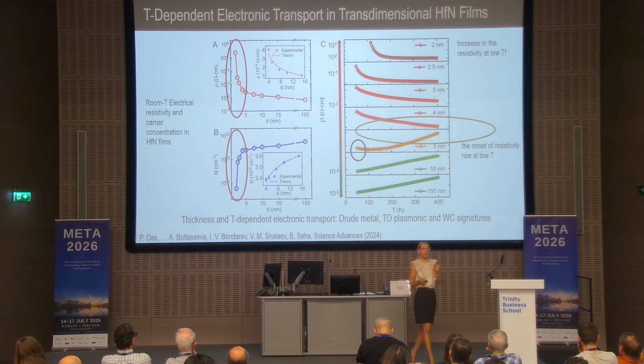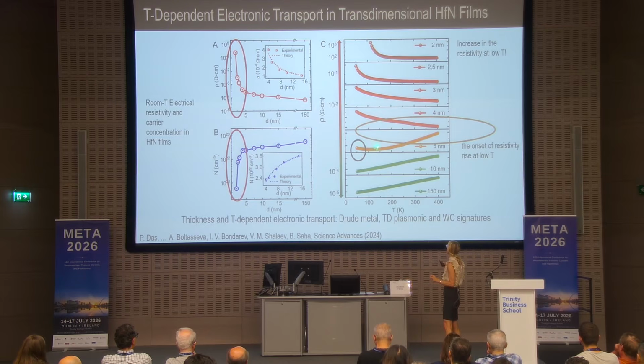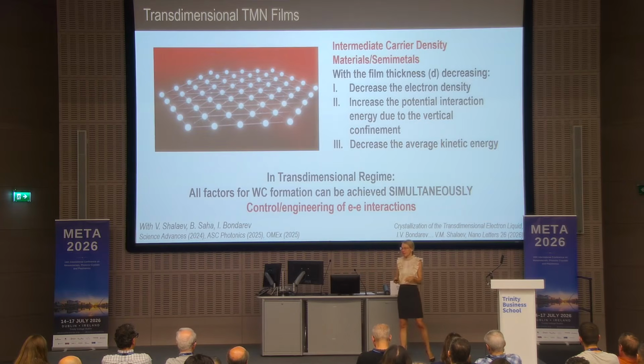And the intriguing point that really can serve as an indication of the Wigner crystallization is that usually when you lower the temperature, you would expect the resistivity to go down. Now for these materials, when you go very, very thin and you lower the temperature, you see the onset of resistivity rise at low temperature. So the low temperature here again is just helping you to localize and freeze those electrons. So this is a very powerful signature of an interesting effect here.